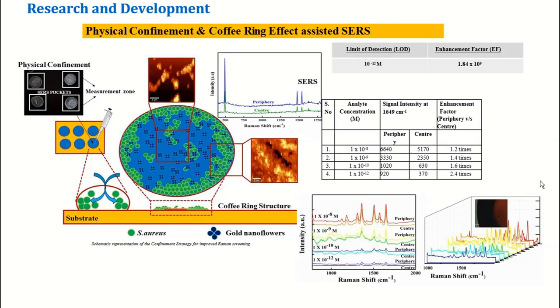This gold nanoflower fabricated by us, synthesized by us, can be used for enhancement of this Raman spectroscopy. And we can detect up to nanomolar concentration. You can see the enhancement factor is 10 to the power 9, and we can detect up to picomolar concentration.